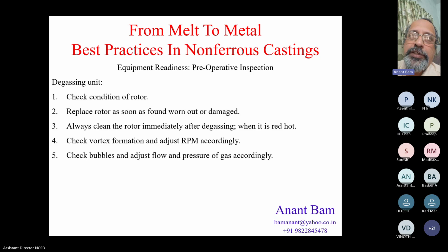And if you find such metallic particles on top of the furnace, then rest assured that your bubble size is perfect. And a vortex with a 4 inch level difference between sidewall and the eye of the vortex, and collection of fine particles of metal on the top of the furnace, are the two indicators that the RPM of your rotor is good and your bubble size is good, and you attain maximum efficiency of degassing in such a condition. Next slide, please.